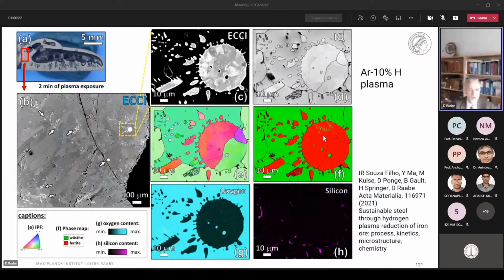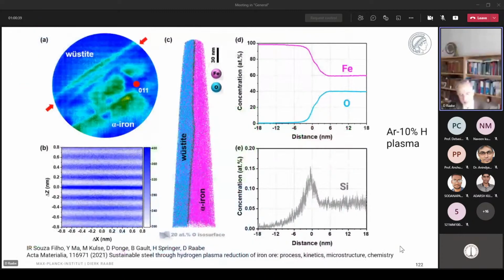So that's very, very efficient. This is just a nice little appetizer picture where you see an iron nucleus in the solidified, quenched iron oxide that surrounds it. That was just one of these intermediate 2-minute tests that we stopped, took out the material to, of course, better understand the nucleation and the growth processes in the liquid.